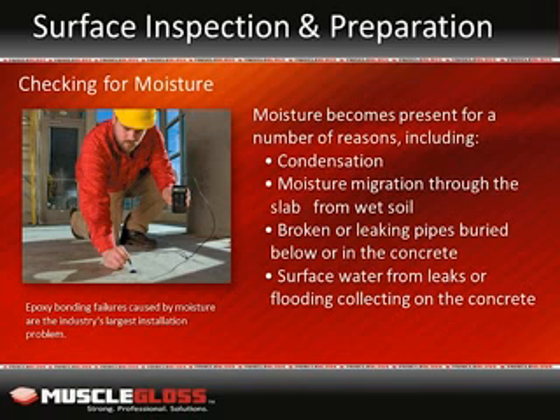ASTM-F-1869, standard test method for measuring moisture vapor emission rate of concrete subfloor using anhydrous calcium chloride. ASTM-F-2170, standard test method for determining relative humidity in concrete floor slabs. ASTM-D-4263, plastic sheet test. This test is only an indication of the presence of moisture and should not be used to determine moisture movement. No matter which test you use, if moisture is indicated, you will need to address the issue before installation.